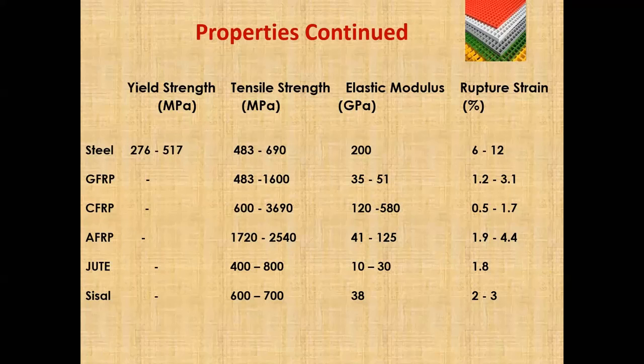Then CFRP, on a similar basis, the tensile strength is of the order of almost 600 to 3690. Elastic modulus is of the order of 120 to 580. Then rupture strain is of the order of 0.5 to 1.7. It has very high tensile strength, but its rupture strain is very low. That's one of the drawbacks of carbon fiber reinforced polymer composites. The aramid fibers also have a good tensile strength, in the order of 1720 to 2540, and the elastic modulus is 41 to 125, and the rupture strain is 1.9 to around 4.4.